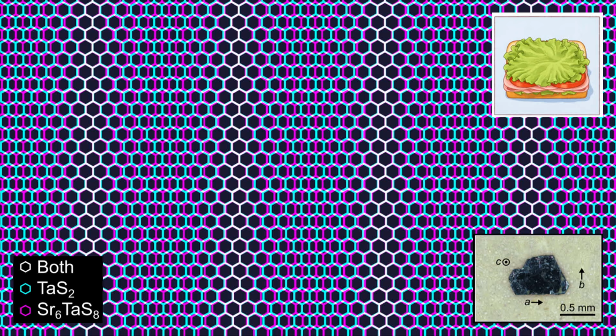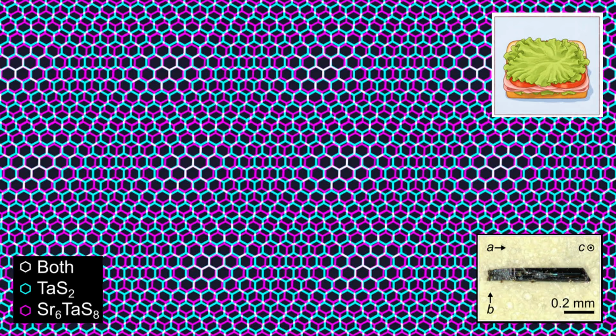So you can see this crystal is aperiodic. It doesn't have a unit cell. And it's typified by this very simple one-dimensional Moiré superlattice here. So certain regions of chemical phase space stabilize structures like this, but other regions stabilize more quasi-two-dimensional Moiré superlattices that can have lattice mismatches in both the x and the y direction.